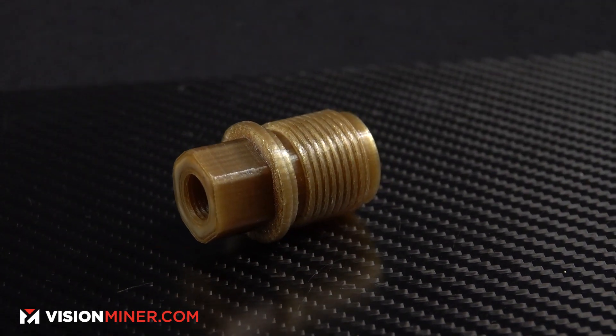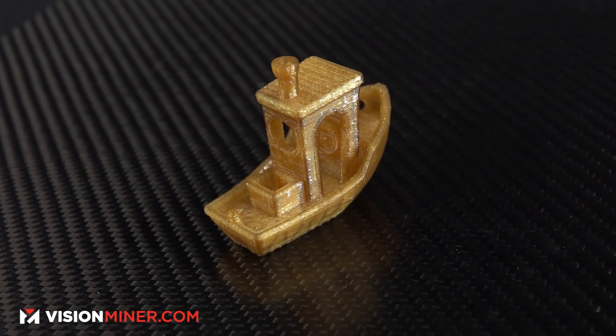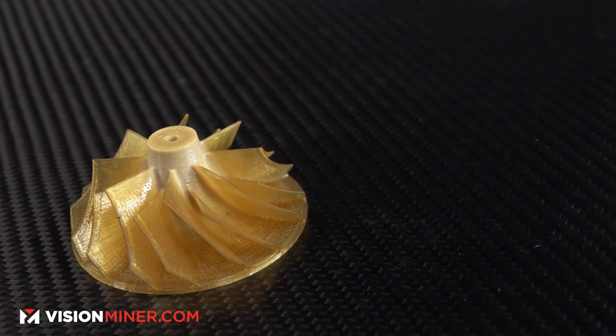What makes this stuff unique as opposed to PEEK? It's amorphous and semi-crystalline. When you print it, it's amorphous — it doesn't have a crystalline structure, so it has a TG and will start failing at a certain point. But when you anneal it, over time crystalline structures actually form and lock it into the shape it's at, and that actually increases the heat deflection temperature, rigidity, and all the mechanical properties significantly — almost doubles them.